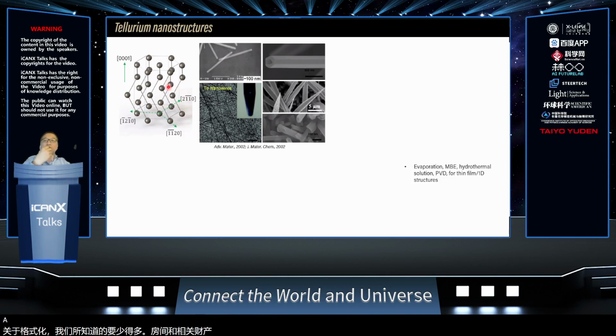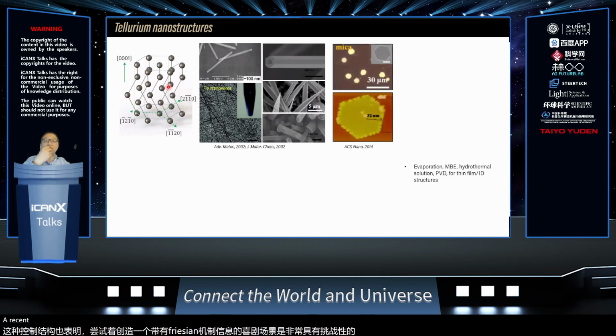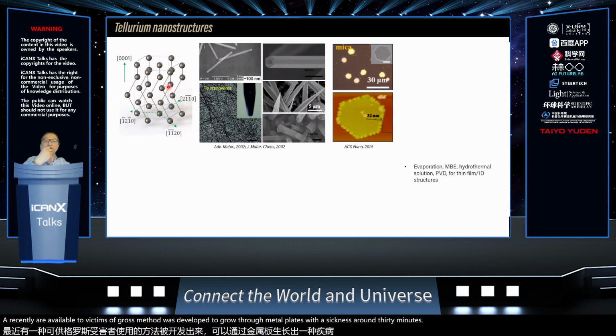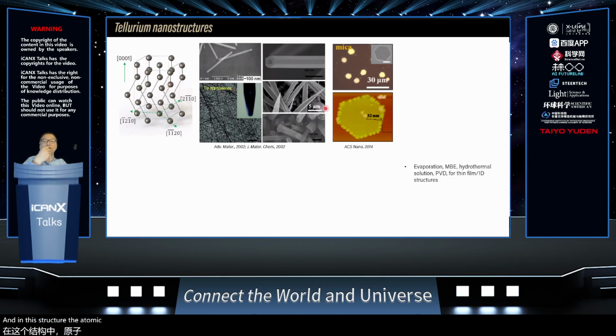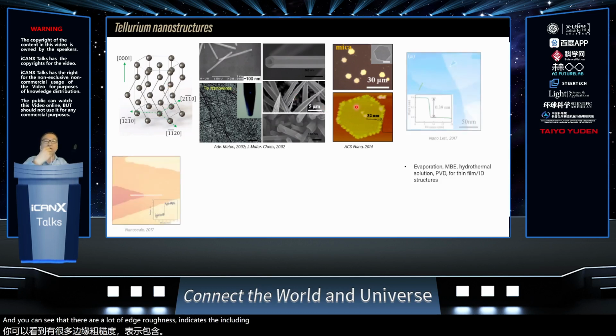This chiral chain structure also indicates it's very challenging to peel off atomically thin flakes with the mechanical exfoliation method. Recently, a van der Waals epitaxial growth method was developed to grow tellurium nanoplates with a thickness around 30 nanometers on mica substrate. In this structure, the atomic chain is oriented out of plane, and you can see a lot of edge roughness, indicating the existence of numerous defects.